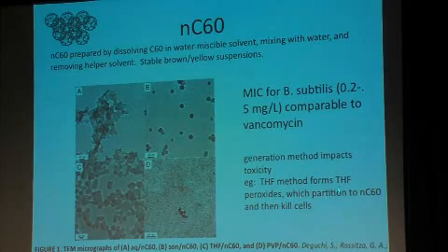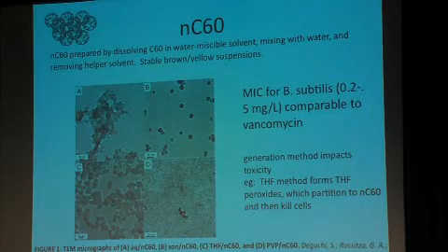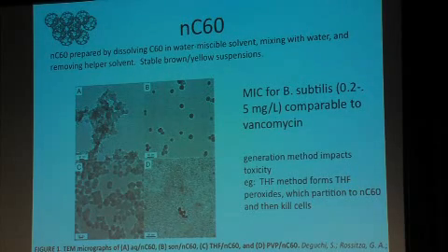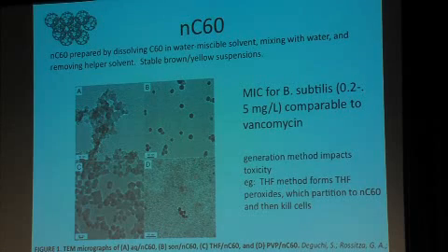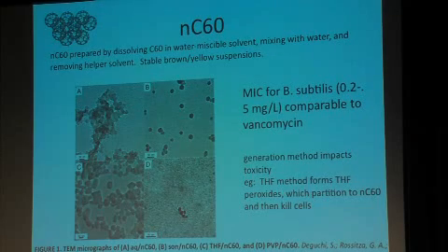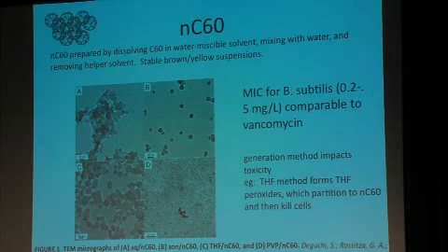And so in this case, the peroxides appeared to be partitioning into these aggregates. And the peroxides were causing oxidative damage, which in turn damaged the cells. Okay, and so what this shows is that you can have aggregates that look superficially pretty similar, and yet they can have different bioactivity because of, in this case, a relic of their synthesis history.